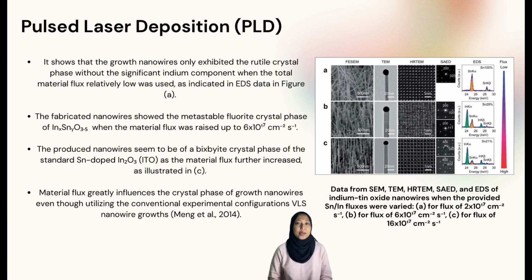This figure represents the PLD method that shows the grown nanowires only exhibited the rutile crystal phase without the significant indium component when the total material flux relatively low was used, as indicated in figure A. The fabricated nanowires show the metastable fluorite crystal phase when the material flux was raised up to 6 times 10 to the power 17 cm-2 second-1. The produced nanowires seem to be of the bixbyite crystal phase of the standard Sn doped ITO as the material flux further increased, as illustrated in figure C. According to these results, material flux greatly influenced the crystal phase of grown nanowires, even though utilizing the conventional experimental configurations of vapor-liquid-solid nanowire growths.